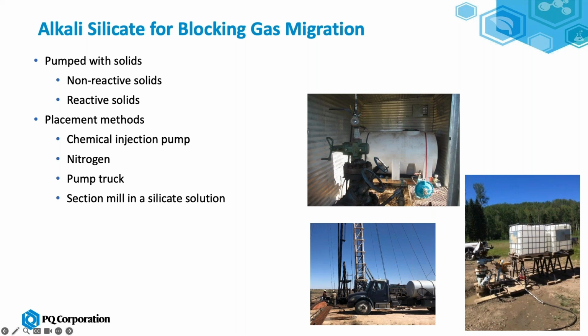Other ways we've seen silicate placed is put in the casing, and these would be for low leaks, so like thread leaks, casing leaks, so very minimal flow past, and to put a nitrogen tank and pressure up the silicate in the casing and just have it slowly squeeze in. So that's been done a few different times quite successfully.